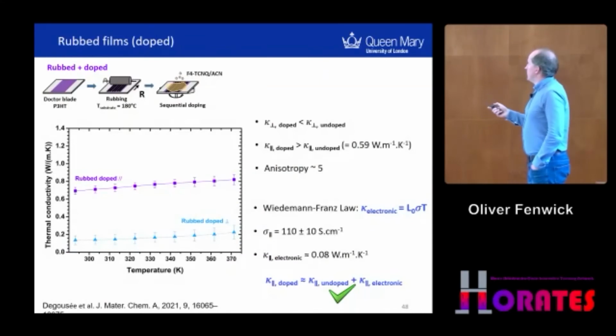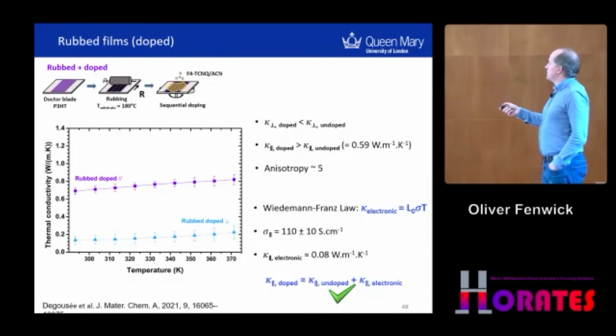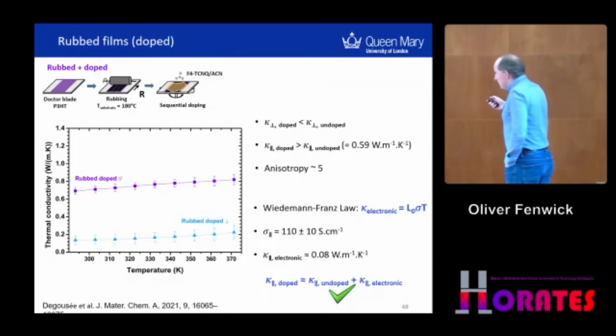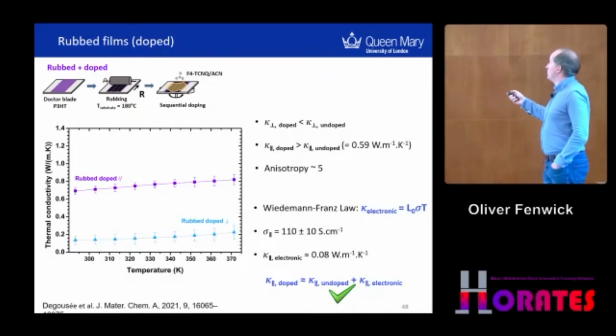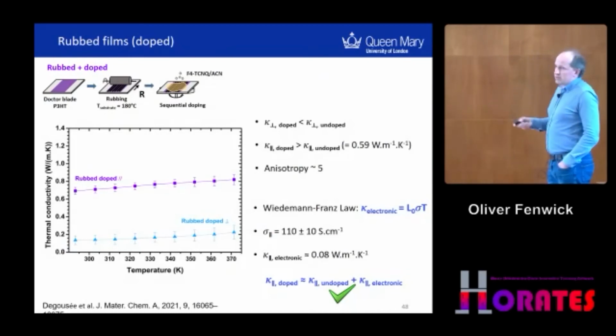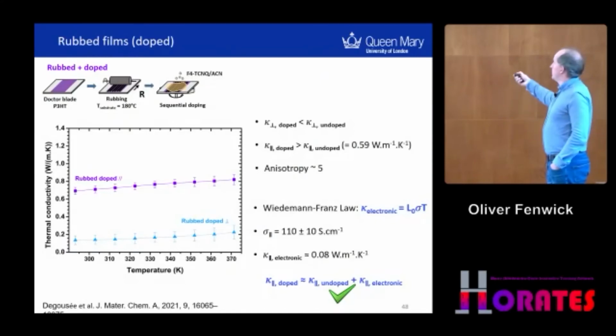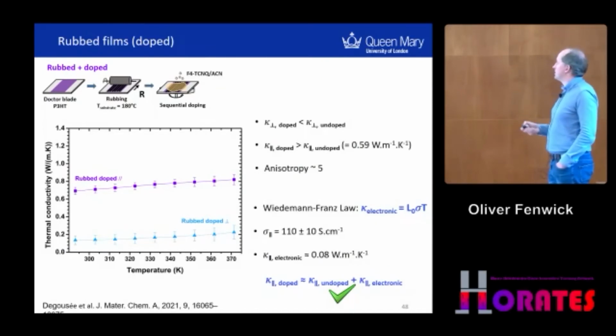Okay, let's dope the films now. When you dope them, not much happens in the perpendicular direction, when the chains aren't aligned with the heat flux. We still have a very low thermal conductivity. When the chains are aligned with the heat flux, we see around 0.7 watts per meter Kelvin. Now, this might be a small structural change, but we should point out that this is also consistent with an electronic thermal conductivity using the conventional value for the Lorentz number. So we'd expect an increase of about 0.08 watts per meter Kelvin, which is within our error bounds of what we do see.